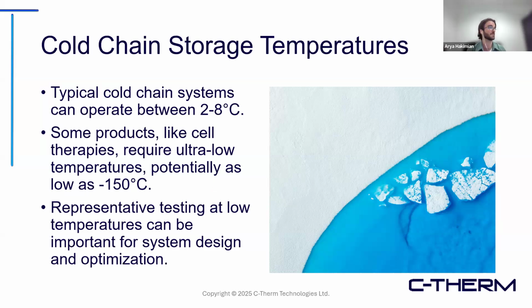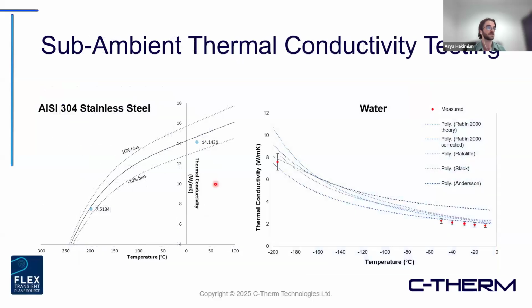And with the TPS method, we have done some testing down to lows just shy of minus 200. Really in that liquid nitrogen environment. So here are some example data sets that were collected on a stainless steel and also water. It would be ice, of course, at that point. But just seeing how that behaves based on certain theoretical assumptions going down that low. So with the TPS, you do have a nice option here to do direct measurements under cryogenic conditions.